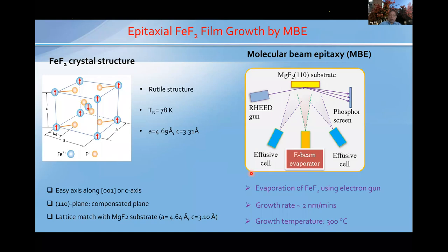To make high quality films, many other researchers have demonstrated the growth of similar films, including manganese fluoride and iron fluoride films by e-beam evaporation. Because of the lattice structure, we have a uniaxial anisotropy for the antiferromagnets. We grow this by MBE, e-beam evaporation in UHV, and we control the rate by controlling the temperature.